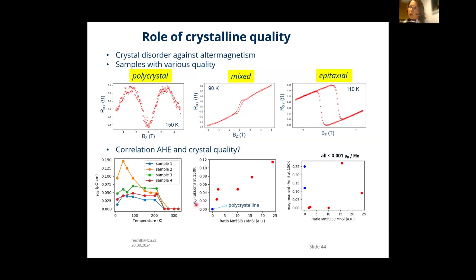we could correlate the anomalous Hall resistivity at, let's say, 150 K. We didn't see anything in the polycrystalline sample, and then it was to some extent scaling. And it was in contrast to the SQUID data, where we measured all of these samples by magnetometry. There is no correlation: whatever we measure there is not correlated with the XRD. So this was the role of the crystalline quality.